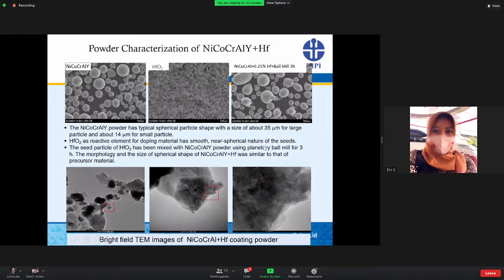TEM characterization has been utilized in order to understand the mixture and distribution of hafnium dioxide in the precursor material, as presented in this figure. These figures show a bright field TEM image of nickel, cobalt, chromium, aluminum with the hafnium additions. The bonding of nickel, cobalt, chromium, hafnium can be observed. Hafnium doping is randomly distributed and surrounds the major particles of the nickel, cobalt, chromium, aluminum.